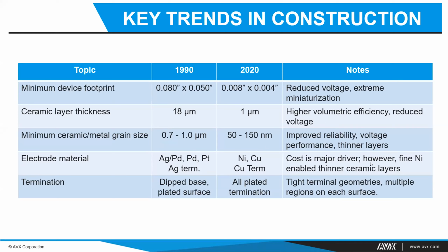However, we found that nickel devices actually enabled us to go to thinner ceramic layers, as the interactions between palladium, which was typical of the electrodes of the day, and the oxidation that would occur on those and then be released throughout some of the heat ramping sections, the firing profiles, actually caused some disruptions in the thin dielectric layers. And so nickel did not go through a lot of those changes, and therefore allowed a more stable thin layer device. And lastly, terminations.